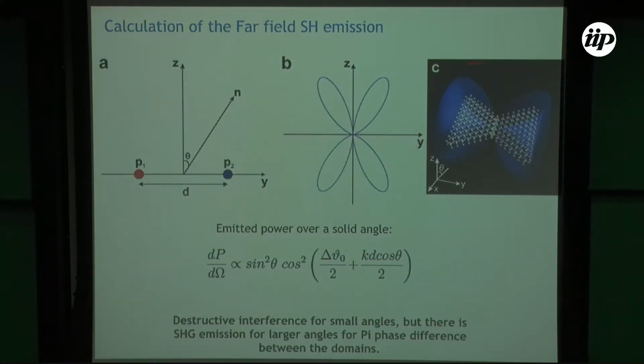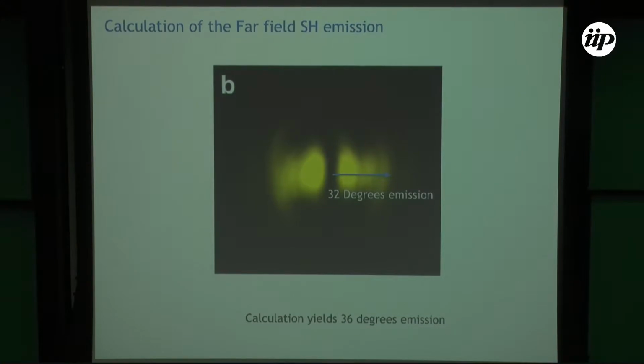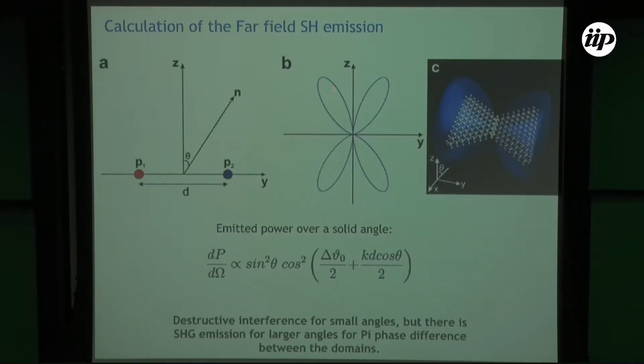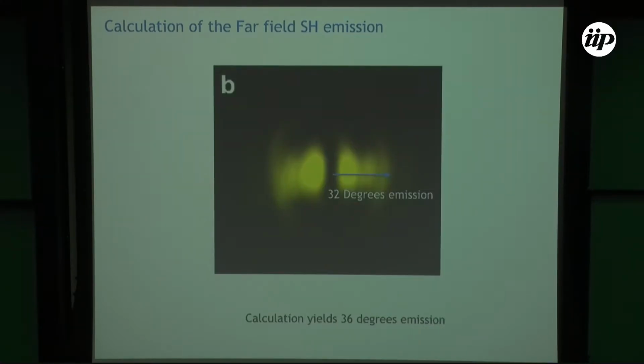This is just a 3D plot to show the same idea. For small angles, there is no second harmonic emission coming from the grain boundary, but for large angles, you have a second harmonic emission. From this calculation, we expect 36 degrees between this and the maximum intensity of the second harmonic. 36 degrees will be the angle between here and this maximum intensity here. And we found in the experiment around 32 degrees, so it matches well with what we would expect.